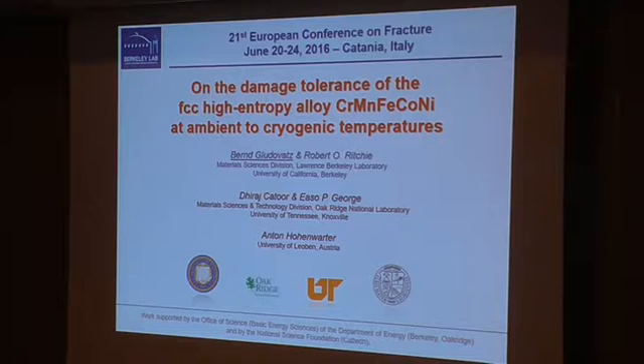The deformation itself was, at lower strains, identified to be carried mainly by planar dislocation slip on {111} planes in <110> directions. This occurred at all temperatures, whereas at the lower temperatures, at the higher strains, above 20% strain, we got, in addition to planar dislocation slip, also nanoscale deformation twinning.